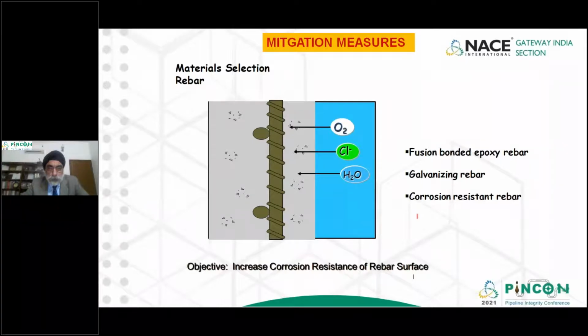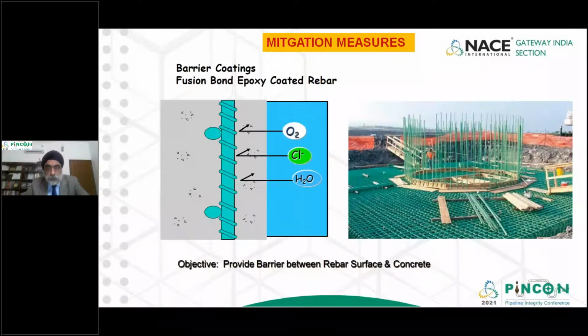Objective is to ensure that steel is not exposed to the corrosive environment, the same way we do 3-layer PE or fusion bond epoxy on our buried pipelines. So this photograph shows FBE coated rebar, commonly known as green rebars. Effectively can be used to mitigate corrosion. One of the strategies is to use a fusion bond epoxy coated rebar, commonly used in many parts of India for constructing bridges in the marine or in a saline atmosphere. You would have seen green rebars in the construction of bridges.